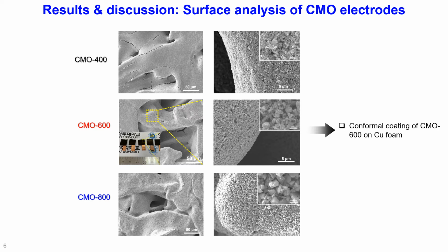Surface analysis of CMO electrodes. Here we have taken some images of the CMO electrodes, that is CMO 400, 600 and 800 electrodes. Among these 3 electrodes, CMO 600 shows the conformal coating on the copper foam substrate, which is due to the optimal particle size and very little aggregation.